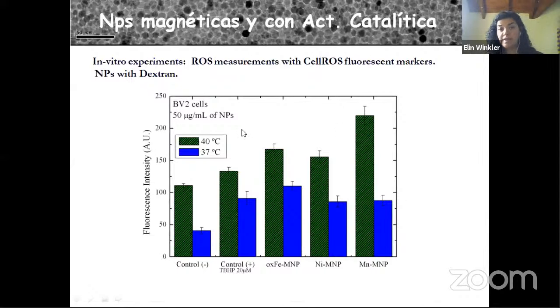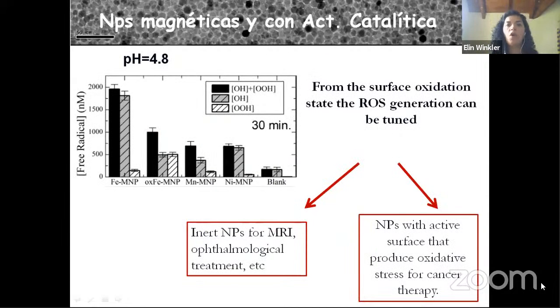And this is the measurement in the cell for the nanoparticles. When we heat the nanoparticles, the system presents a large concentration of free radicals. So we finish the results. The only message that I want you to keep is that when the nanoparticle presents iron 2+ on the surface, it has a very large concentration of radicals, and when they are oxidized, their concentration of radicals drops. In that way, we can tune it: if we want to produce free radicals and cell damage, we have to use a reduced surface.